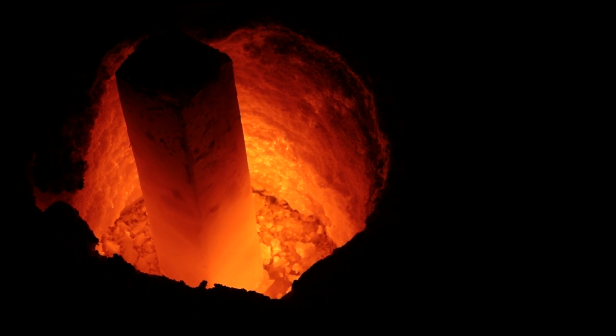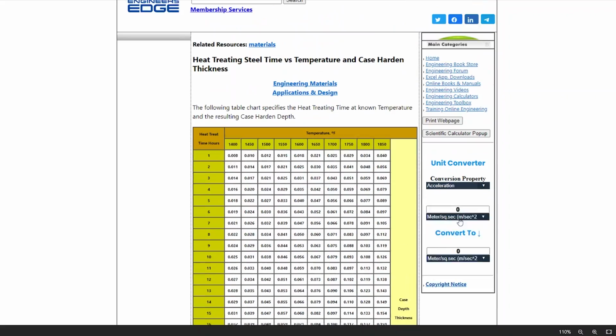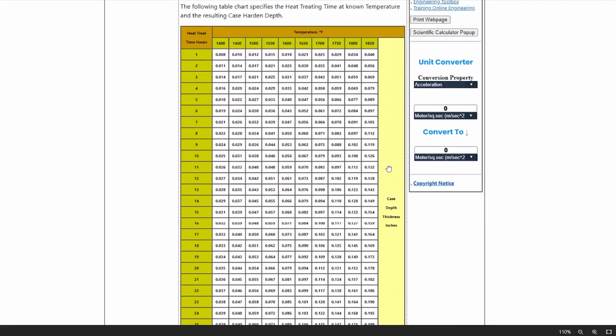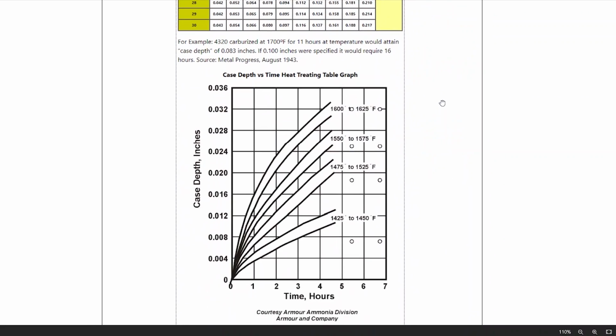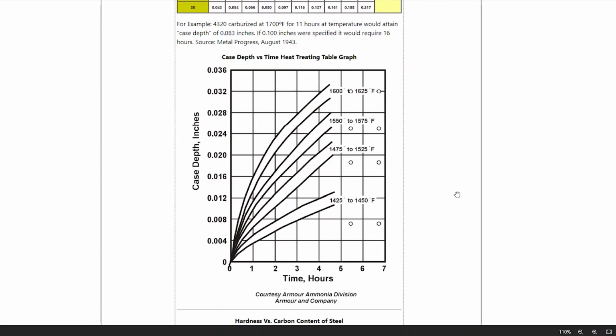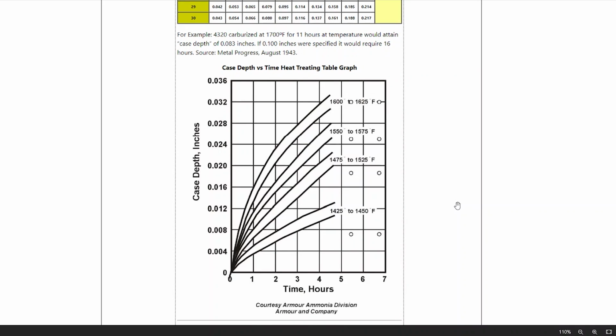Now the carbon builds up on the outside of the steel and it works its way into the centre at a rate of about 0.01 to 0.02 millimeters per hour. It's a very slow process, and I've seen videos where people will spend days maintaining furnaces to get the carbon to diffuse deeply into a piece of steel.